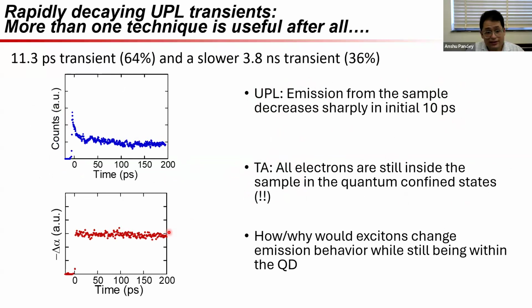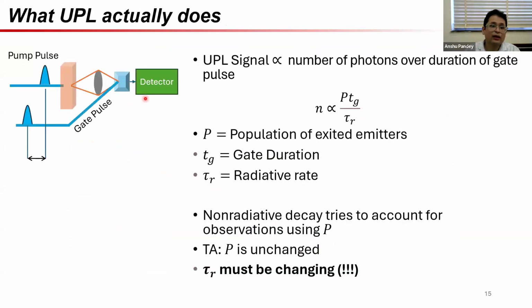So the sample is doing something which is actually over this time causing it to emit less, even though nothing got de-excited at all. So the electrons never moved, and yet the sample's emission lifetime changes. How could this even be possible? They are all sitting in seemingly the same state as far as TA is concerned. So this is really a surprising result.